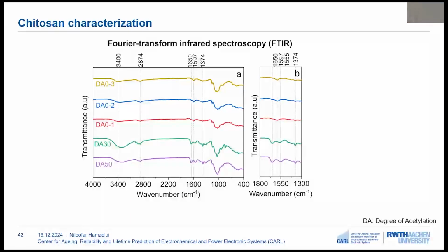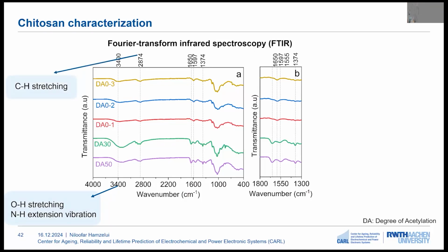First, the chitosan biopolymers were investigated using FTIR measurements. And here we can see at 3,400 the OH stretching and the NH extension vibrations. Also for all the samples, we can see the CH stretching. And in the region between 1,500 and 1,800, this is where we can estimate the DA of the chitosan binder due to the amide and amine bands.